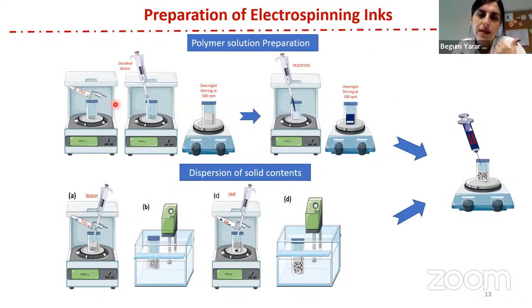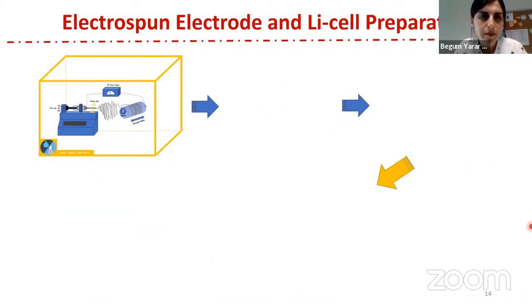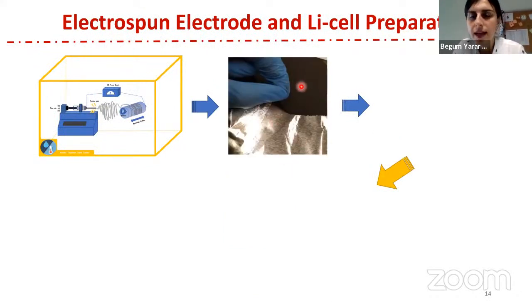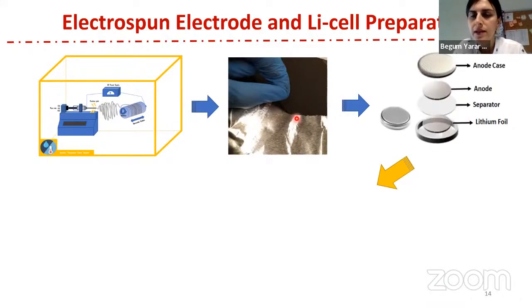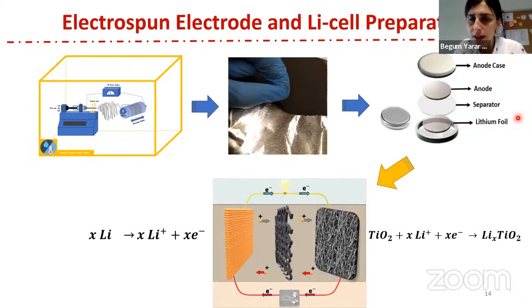The procedure is the same as for the electrodes for PEM fuel cells. We are preparing a polymer solution, and we are preparing a solid dispersion, and we are mixing it, and we are directly electrospinning it. First of all, we are electrospinning the inks, and we obtain this flexible electrode, and then we prepared a lithium cell. In this lithium cell, we didn't use any current collector. This gives the opportunity of a lighter lithium-ion battery design,